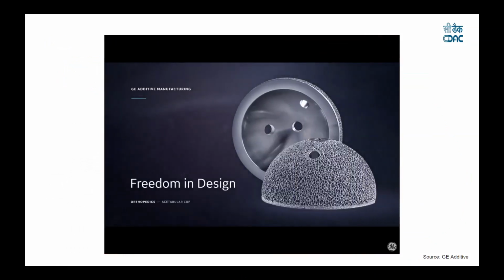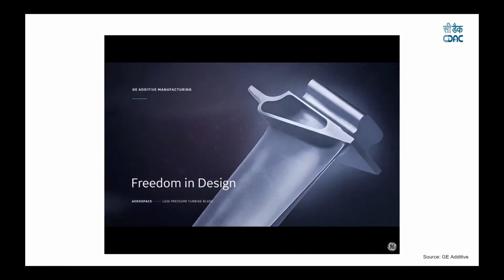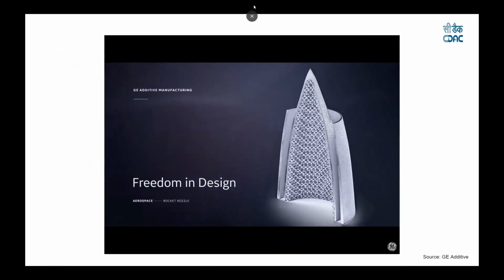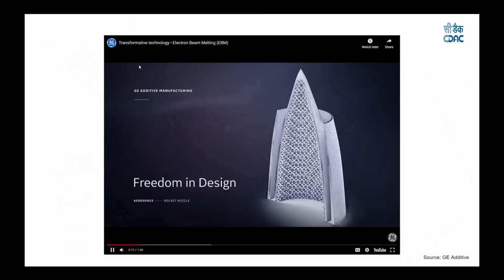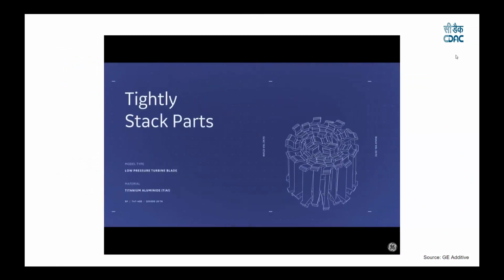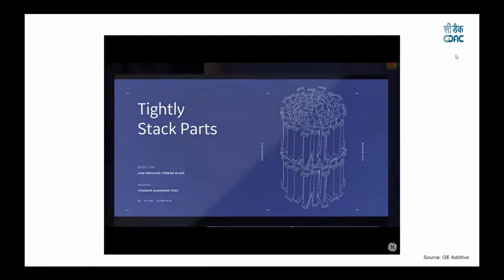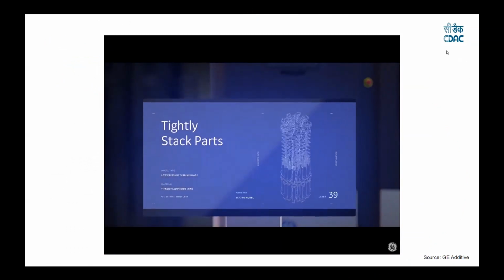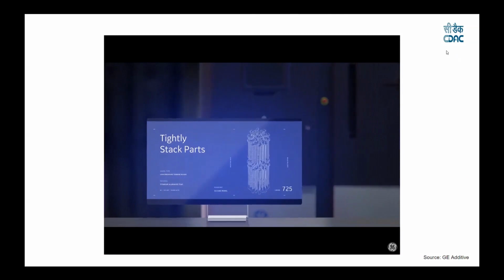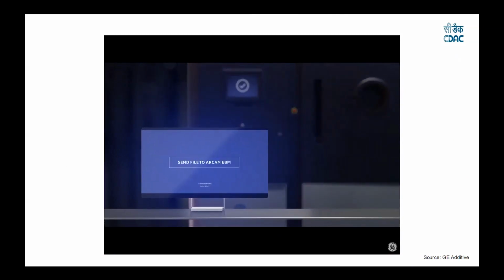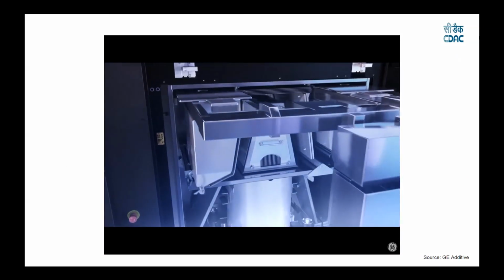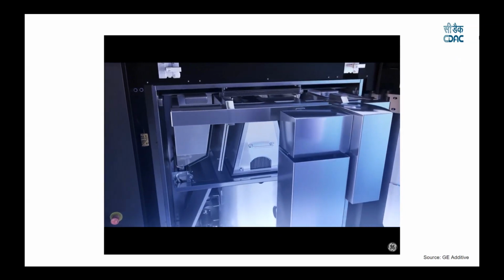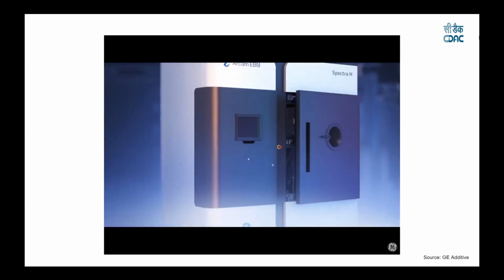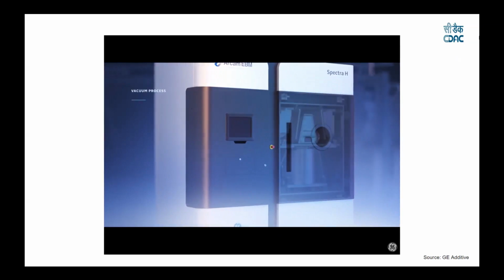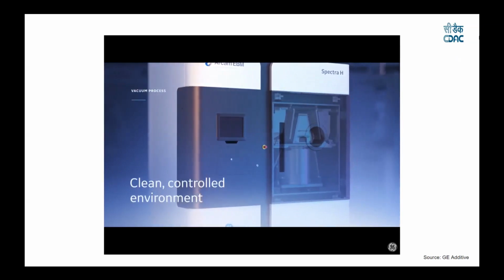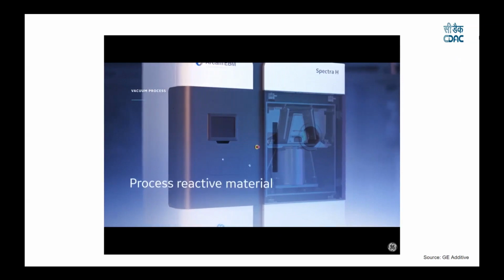Additive manufacturing offers greater freedom in design and allows for the creation of optimized parts that are not constrained by the limits of traditional manufacturing. Arcam EBM has the unique ability to tightly stack parts within the build in order to increase productivity. An optimized build file is sliced and loaded into the Arcam EBM system. Following this, metal powder is loaded into the machine. The chamber is then closed and a vacuum is created to ensure a clean, controlled environment that allows for the processing of reactive material.